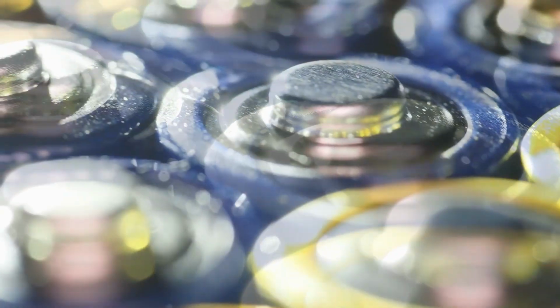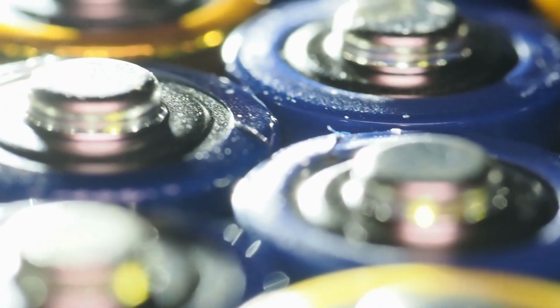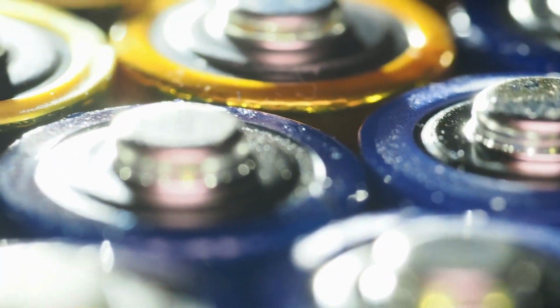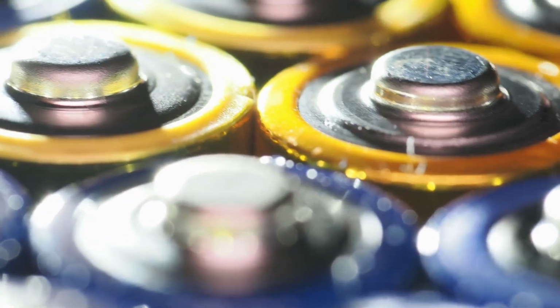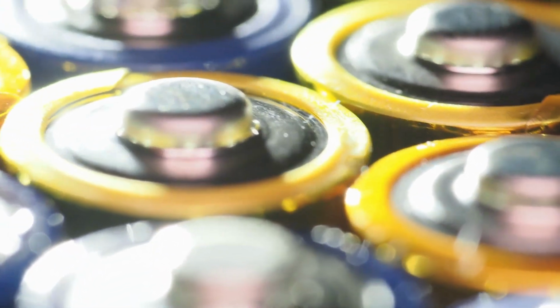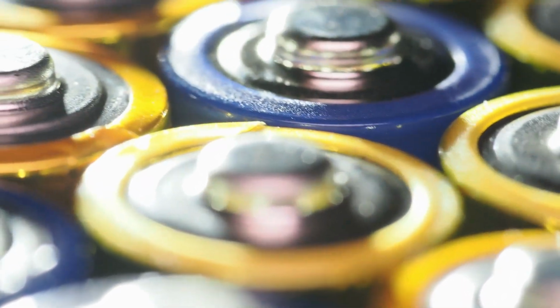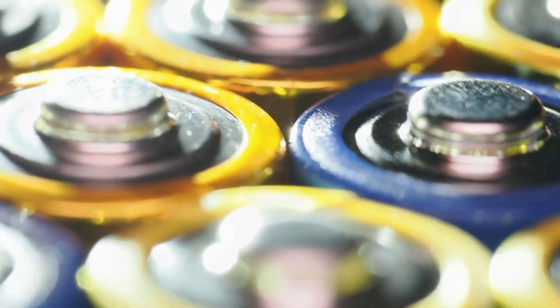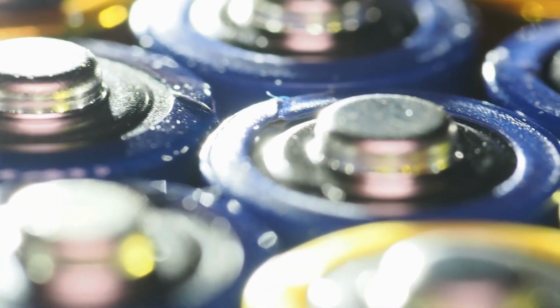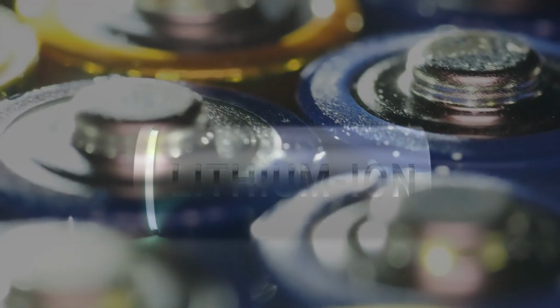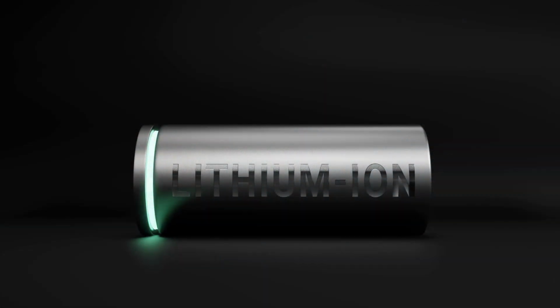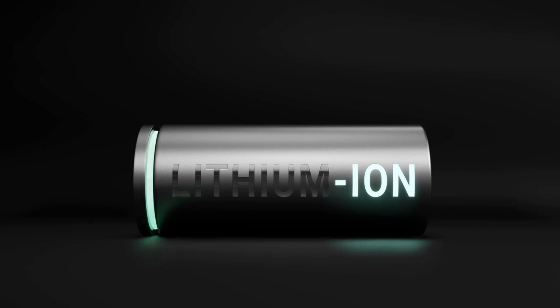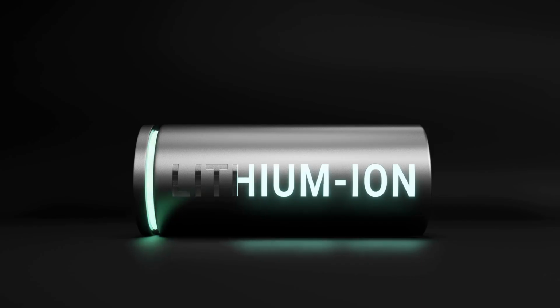But they don't. Instead, they form a thin, protective layer known as the solid electrolyte interface, or SEI. It's a kind of chemical shield protecting both the graphite anode and the electrolyte from further reactions. But crucially, lithium ions can still slip through it. When the SEI originally forms during the first charging cycle, around 5% of the lithium in the cell actually gets stuck in this layer, decreasing the battery's capacity.